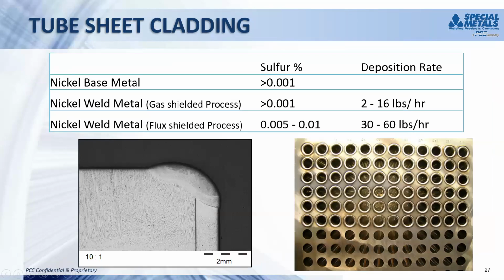So the other big advantage to doing that is tube sheets. The tube sheets come in contact with some of the more corrosive media in a reactor or in just a heat exchanger in general. So when you're cladding for a tube sheet, you run into an additional problem. All of a sudden your weld metal, after you've put all that clad down and machined it, is now the base metal. So it's got to be held to the same standards you would as a base metal. So one of your challenges becomes keeping the sulfur in that weld metal incredibly low.